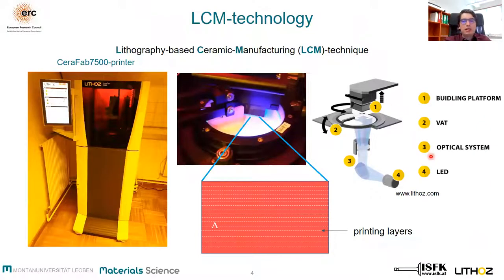All samples in the study were fabricated using the lithography-based ceramic manufacturing technology, LCM, which was developed by LITHOZ. This novel LCM printing system consists of a building platform which is lowered into a transparent rotating vat filled with a photosensitive ceramic polymer slurry. During the layer-by-layer printing process, the slurry is exposed by light through a projection system from below, allowing layer-by-layer fabrication of bulk materials.